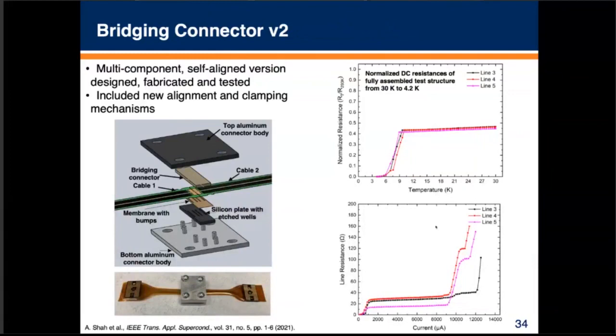We didn't get to the point of doing microwave tests on this because we frankly jumped to another structure that I'll show in just a minute. But we did see some promising results in terms of the DC performance. So we saw the traces transition, and we could see their critical currents. Essentially, you see multiple critical currents here, that's associated with each of those, most likely each of these pieces, right? The traces as well as the small superconducting portion on the connector itself.